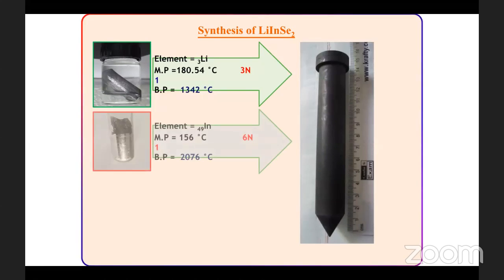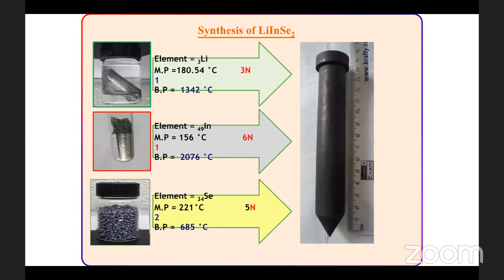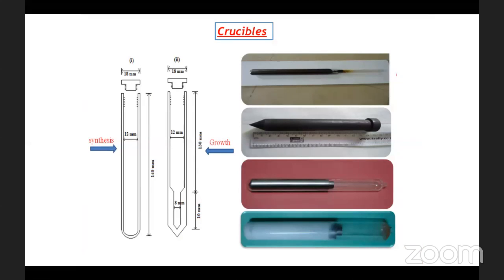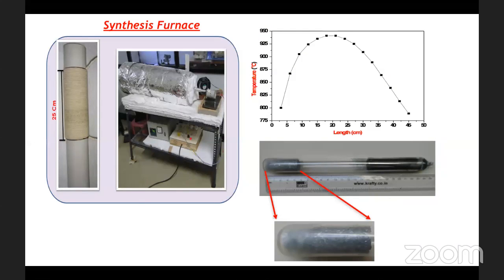For this Bridgman crystal growth, my container is a graphite crucible. Because lithium reacts with quartz tube, I couldn't grow using a quartz tube as a crucible. So I have chosen graphite as a crucible. Once the material is loaded inside the graphite crucible, then you have to seal it. Here you can see, after putting the graphite inside the quartz tube, we did sealing here. You can also see that even though I used graphite, the lithium vapor comes out and reacts with the quartz tube. So that is why you have to select the proper crucibles.